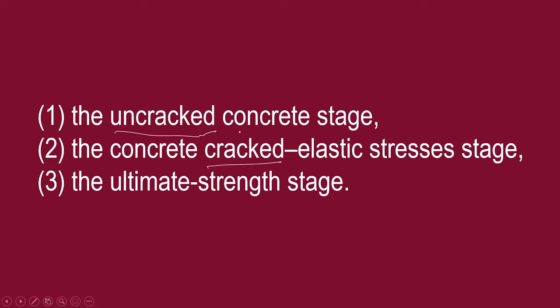Okay, so to solve for Mcr, we need the value of the modulus of rupture. To solve for it, we have the formula here. The modulus of rupture for NSCP 2015 is 0.62 lambda square root of fc prime. The problem is normal weight, so the value of lambda we will use is 1.0.